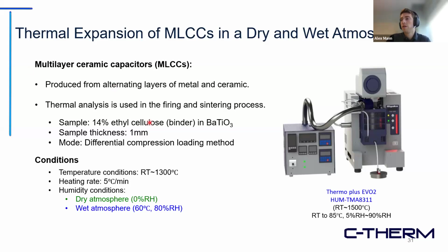We can see here our conditions are room temperature to 1300. We have one test where a dry atmosphere was being pumped into the TMA, and another one where a wet atmosphere - 60 degrees Celsius and 80 RH - was the gas being pumped into the furnace.